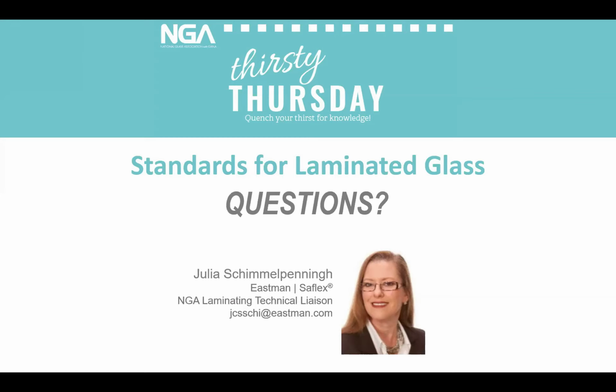Typically, the medium to high range will cover many of the applications, but a baseline, and that's the reason why there's a low, medium, and high, and not more delineation in it, is because there isn't a baseline that's good for everything. And so you really do have to understand your application and the interlayer products and what you're shooting for, no pun intended, for your application and your product. So, but in general, a medium to the high side will cover a lot of the architectural applications.